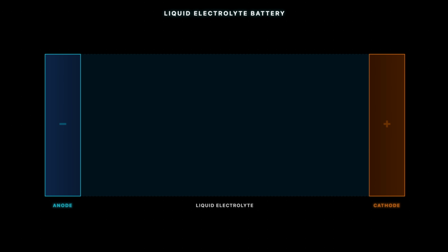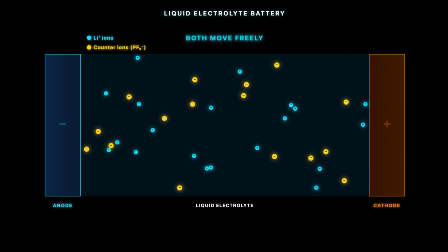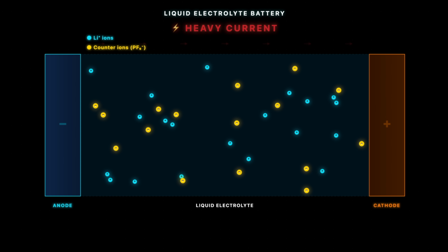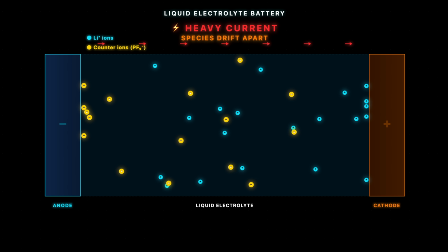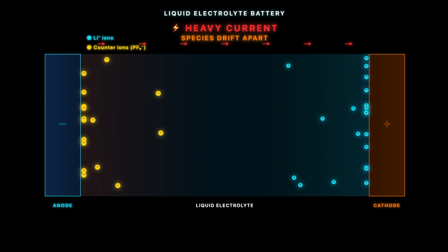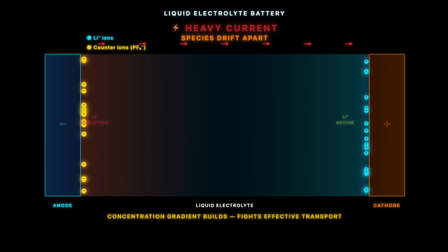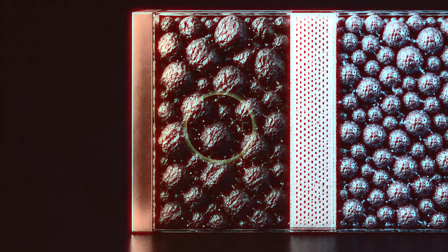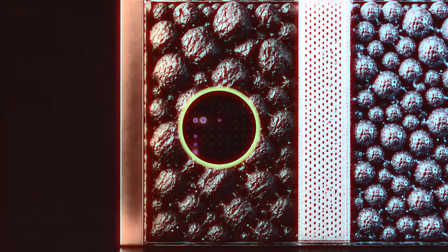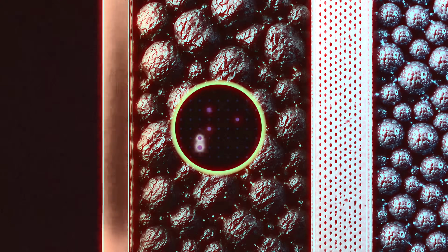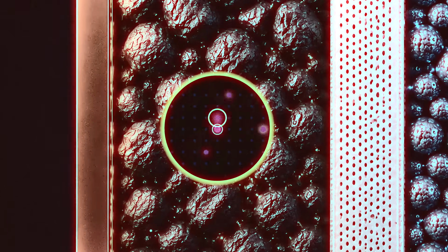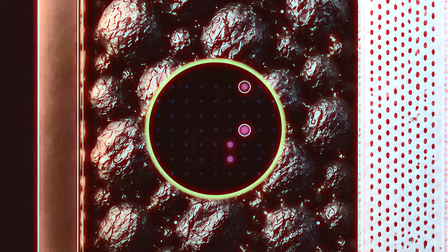In a normal liquid electrolyte battery, lithium ions and their negatively charged counter ions both move freely through the liquid. But under heavy current, the two species start drifting apart, building up concentration gradients that fight effective transport. Battery engineers call this concentration polarization, and it's a big reason your phone charges fast to 20% and slows to a crawl at 80. Conventional solid-state batteries fix concentration polarization by locking the negative ions into a rigid crystal lattice. Now the lithium moves, but has to hop between fixed atomic sites, and every hop costs activation energy. The result is dramatically lower conductivity, which means painfully slow charging for the end product.